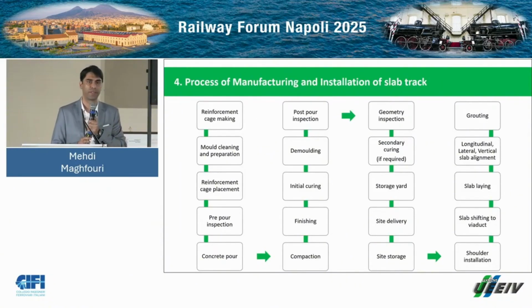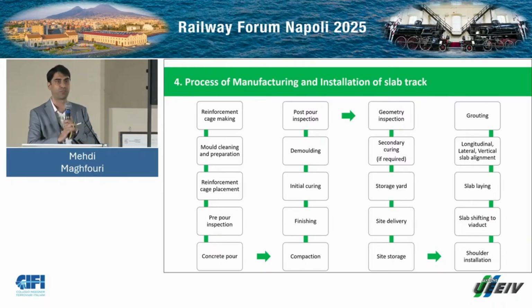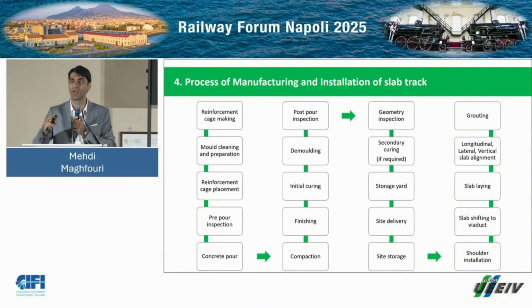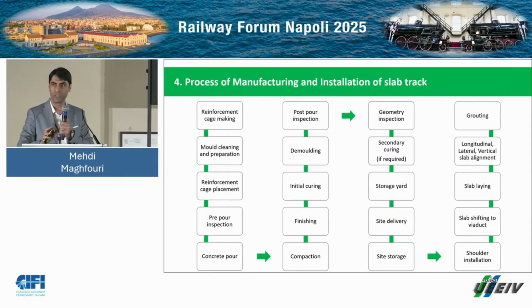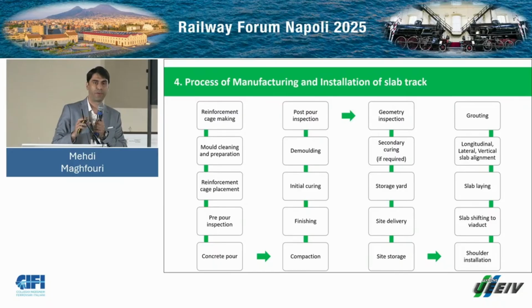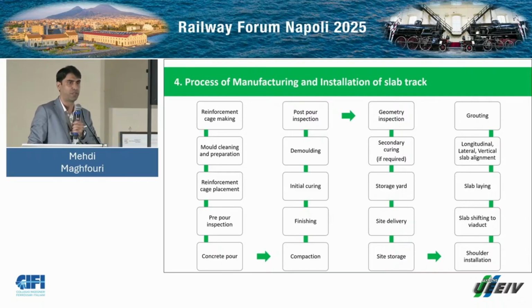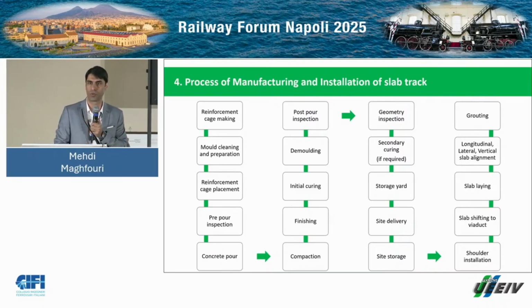But before I discuss the defects on the slab tracks and preventive measures, I would like to draw your attention to the process of manufacturing and installation. Basically, the first stage is the reinforcement cage making, which can be done in parallel with mold cleaning and preparation. Once the mold cleaning is done, then the fabricated steel cage can be placed inside the mold, followed by the concreting. Of course, before the concreting, we need to have the inspection of the reinforcement and mold again, because we don't want to face any issue later on, and then proceed with the concrete pouring.